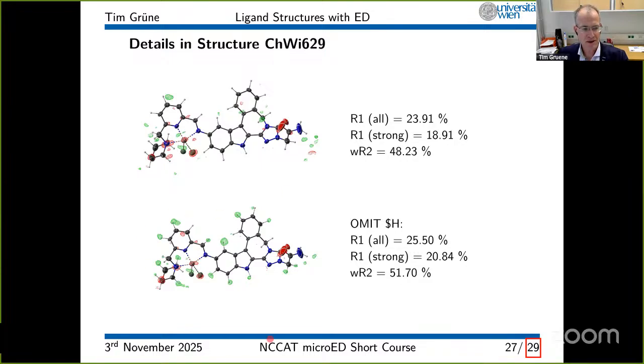Just for completeness here, I calculated an omit map. So this map, a difference map, was computed without taking the hydrogen atoms into account. And you see very strong peaks for all of the hydrogens, even though the crystal diffracted to like 0.8, 0.9 angstrom, and the data were incomplete. If you would have such a quality data set from X-ray diffraction, you would most likely not see the hydrogen atoms. And that's one of the strong points of electron diffraction. The relative strength of light atoms is much higher compared with X-rays. So if you're interested in hydrogens and enzymes, for example, electron diffraction not only gives you the crystal structure from very, very small crystals, it also gives you a stronger signal from what you're actually interested in.